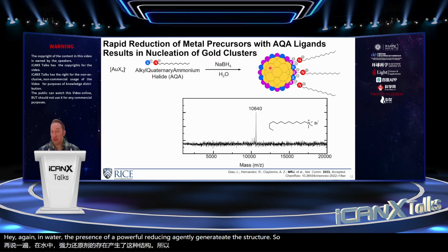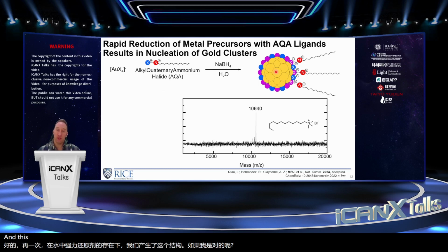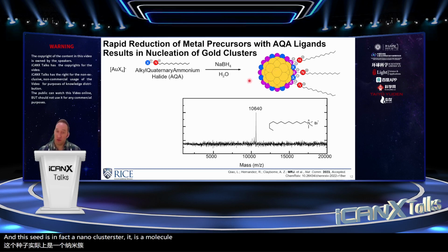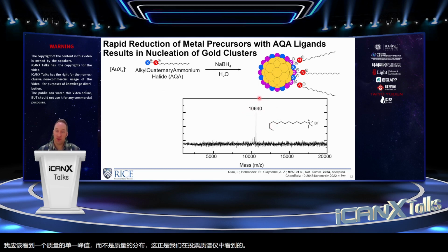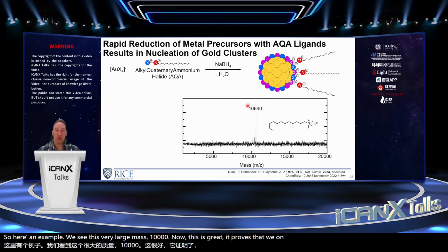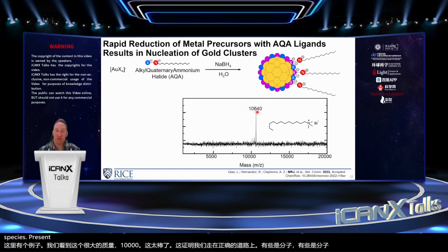So if I'm right, and this seed is in fact a nanocluster, it is a molecule, which means that if I were to do mass spec, I should see a single peak of one mass, not a distribution of masses. And that's exactly what we see in mass spec. So here's an example. We see this very large mass, 10,000. Now this is great. It proves that we're on the right track. There are molecules, some molecular species present, but this doesn't tell me anything about what it is, right?